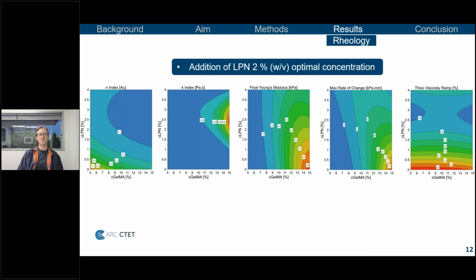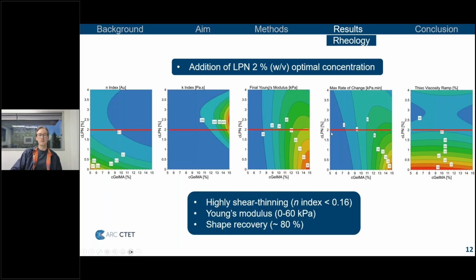So in summary for the rheology, we were able to show that the addition of laponite at 2% was the optimal concentration, which can be seen as this red line here across our key values, such as your n index, which is your shear thinning characteristic, your K, which is your velocity gradient, the final Young's modulus that you're able to achieve, the rate of change, which is your cross-linking kinetics, and also the shape recovery, which is your thixotropic viscosity ramp. So with the addition of laponite at 2% and GelMA 5 to 15%, we have a highly shear thinning capability with an n index of less than 0.16. The Young's modulus can be tailored from 0 to 60 kilopascals and has a shape recovery retention of approximately 80%. So laponite 2% was then deemed the optimal concentration moving forward to add to GelMA.